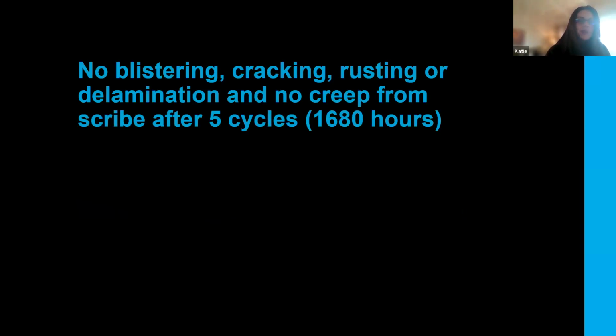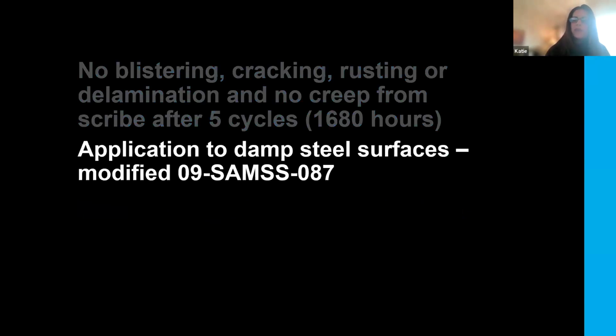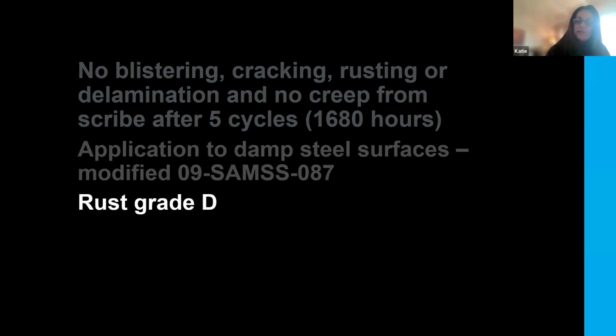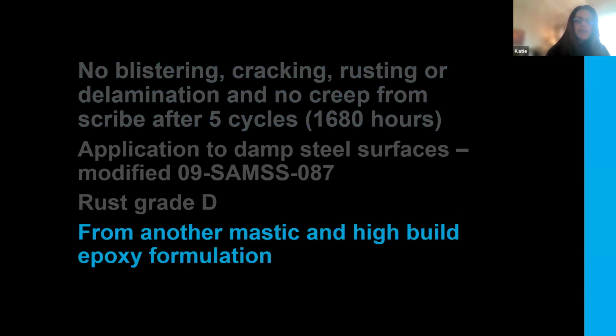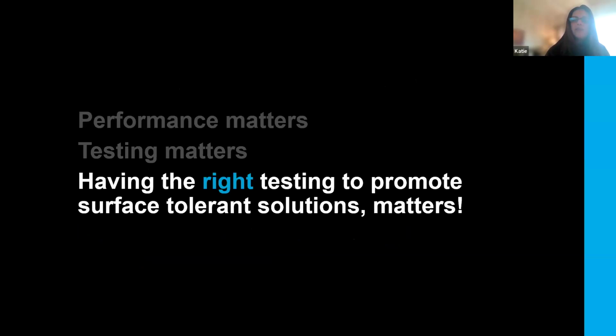How about no blistering, no cracking, no rusting, no delamination, no creep from the scribe after 5 cycles, which equates to 1,680 hours. That's a real result after a modified Aramco test with application of both coats to a damp surface. Over a rust grade D, that's the worst one, by the way. And that one comes in from another epoxy mastic high build formulation. So again, very good results from an existing coating. So performance matters. Testing matters. Having the right testing to promote surface tolerant solution also matters. So do all surface tolerant coatings perform this way? No. But having the right test data does help us make the right decisions.